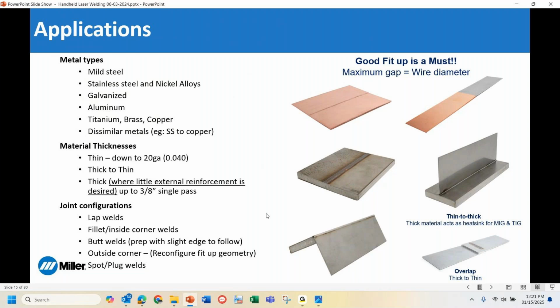So any duct work or products that are going to be manufactured for outdoor environments, that low heat input helps prevent the excessive burn off of the zinc in the galvanized materials. Aluminum is very highly heat conductive and can sometimes be difficult to weld with conventional processes, especially when we look at thin aluminum. And then you look at other materials like titanium, brass, copper.